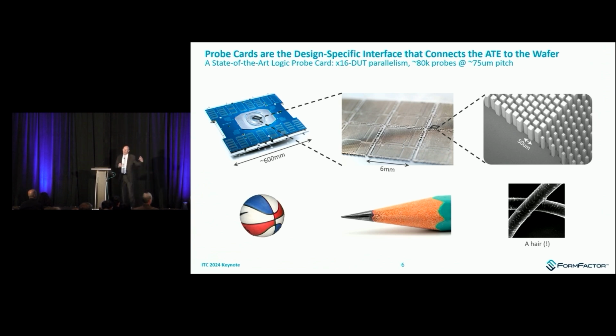So we'll start at the left, with the thing that you see when you see a probe card. It's a great big printed circuit board, somewhere around twice the size of a basketball. That size is driven mostly by the interface to the ATE, the size of the test head, the connector layout, that kind of thing. But as we zoom into the center, which is the probe head, you start to see some of the complexity. And you see a collection of 4+ die here on the 16 die probe card.